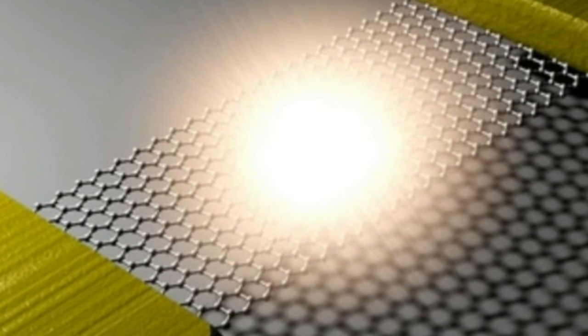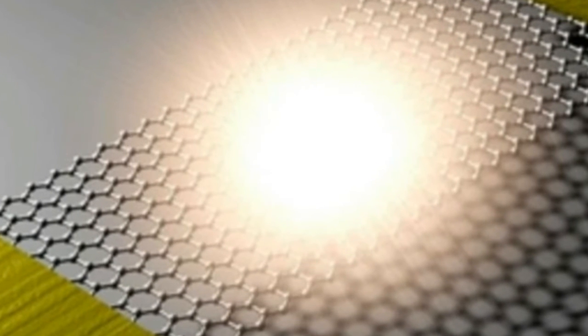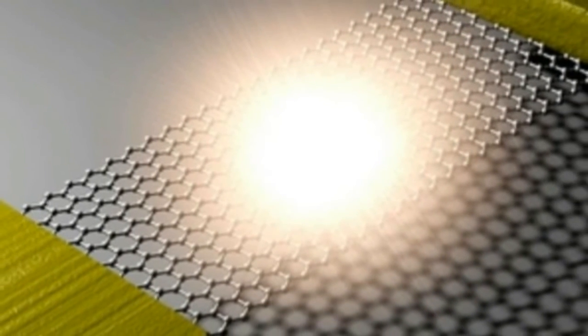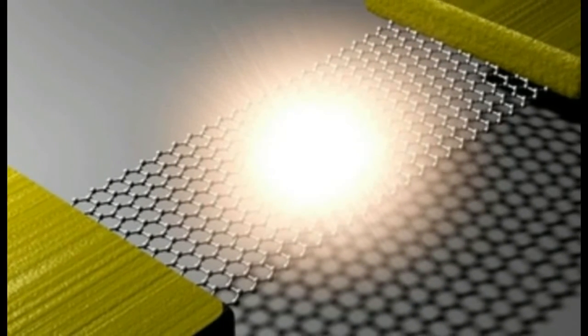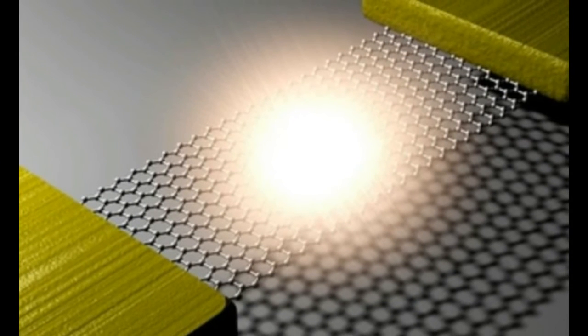It's also the reason the electrodes at either end of the graphene don't melt. As for why this is the first time light has been made from graphene, study co-leader Yung Woo Park, a professor of physics at Seoul National University, noted that graphene is usually embedded in or in contact with a substrate. Physically suspending graphene essentially eliminates pathways in which heat can escape, Park said.